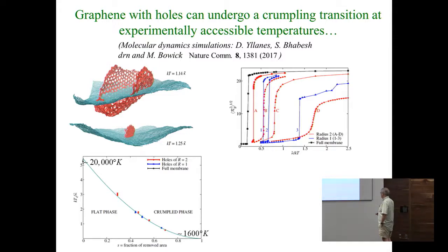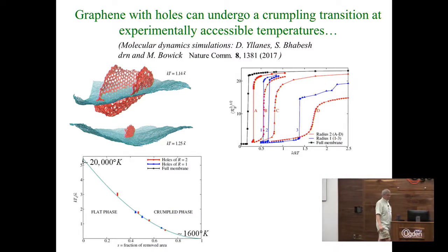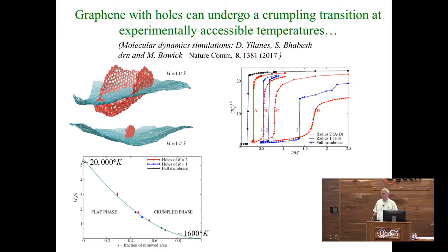But we can estimate from these computer simulations, which I'll show you in more detail in a minute, that if you can remove 85% of the area, you can get this crumpling transition down from 20,000 degrees Kelvin to 1,600 degrees Kelvin, which is probably accessible for graphene in a vacuum. Yes, please.